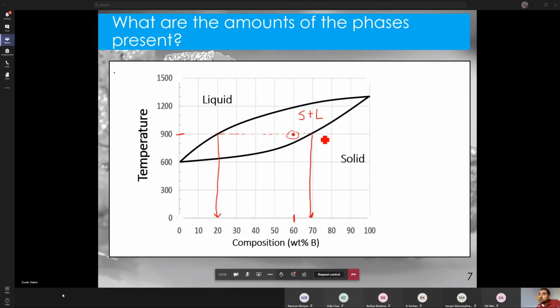But the amounts of the two phases changed. There is now more solid in this crucible, and the reason I know there is more solid is this point has now moved closer to 100% solid. And I can calculate the amount of solid. Remember, always take the opposite side of the lever. Solid is here, so take this distance. So the amount of solid is equal to 60 minus 20 divided by the total length of the lever. And the total length of the lever is 70 minus 20. So we now have 40 over 50. So the material is now 80% solid. And of course, 20% liquid.